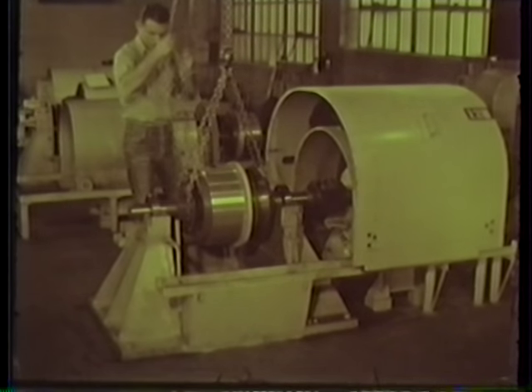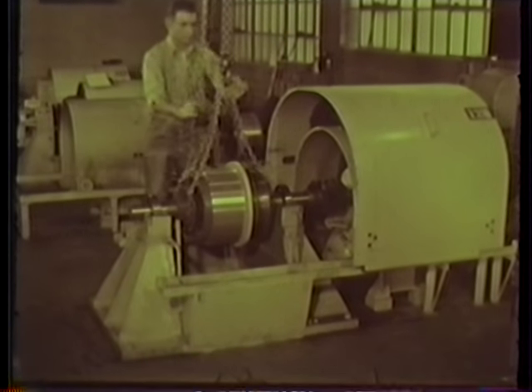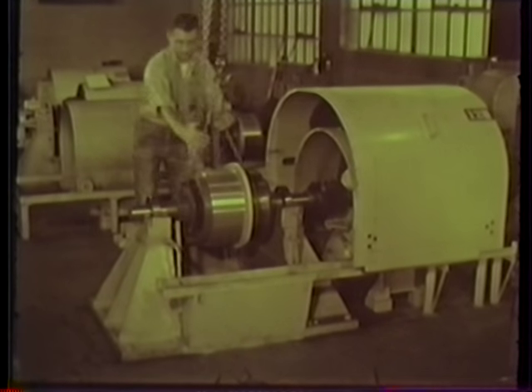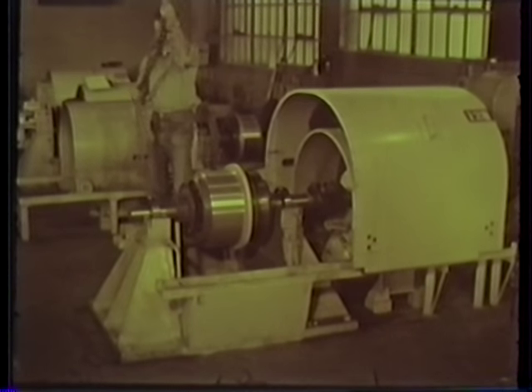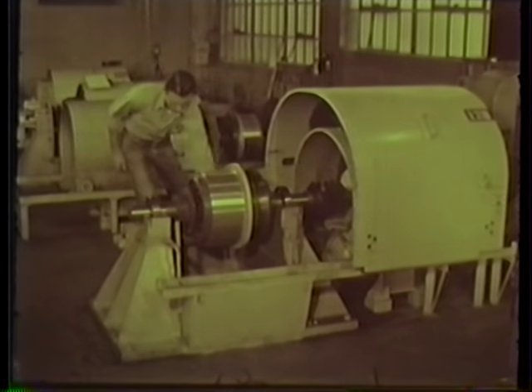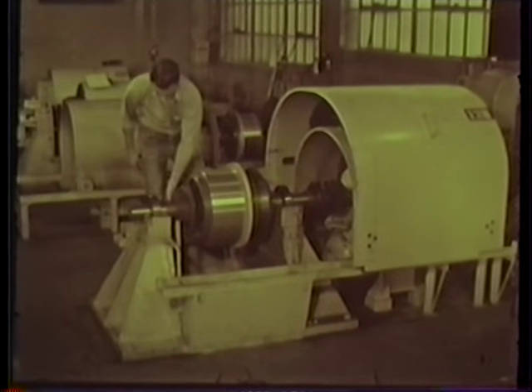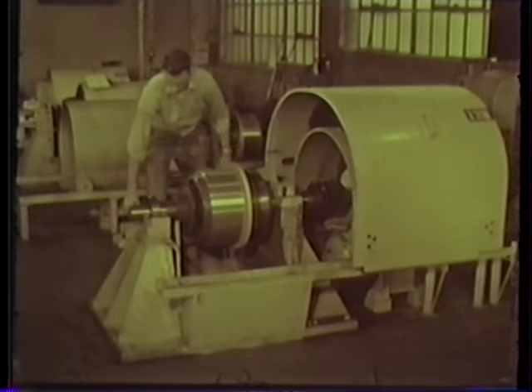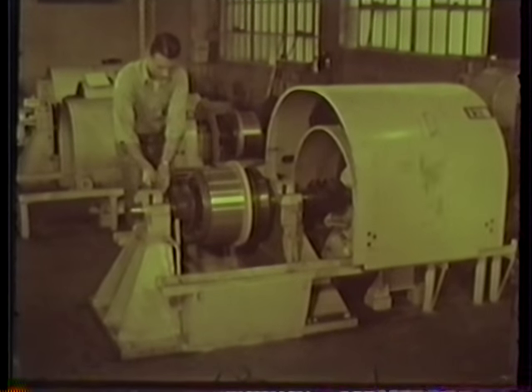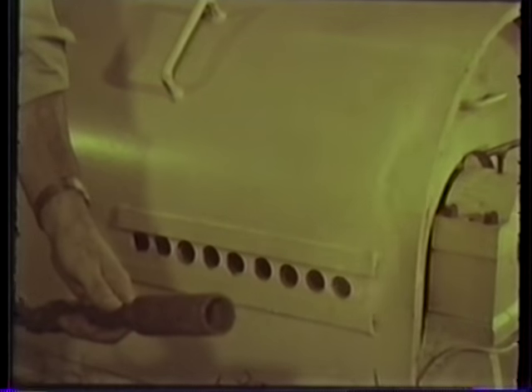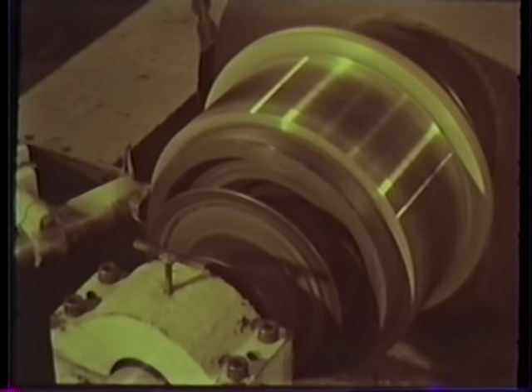Traction motor commutators receive an additional processing step, known as spin seasoning, to assure smooth operation. In spite of a thorough pressing and baking cycle, the tremendous centrifugal forces and temperature extremes encountered in unusual service may cause the segments to readjust themselves, resulting in a rough commutator. This series of high-speed spinning cycles under heat is one of those additional precautions taken to assure no in-service trouble after the commutators are installed on the armature shaft. A final surface finishing step takes place while the commutator is still mounted on the spin table.